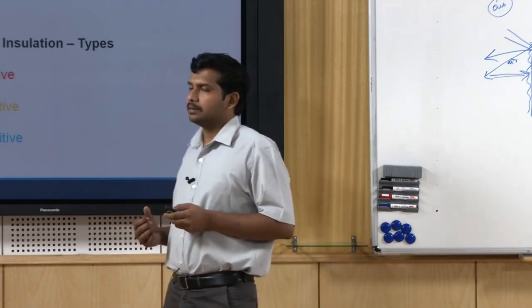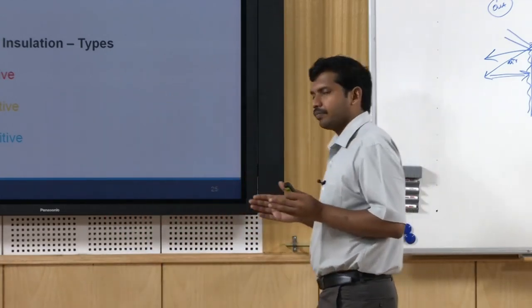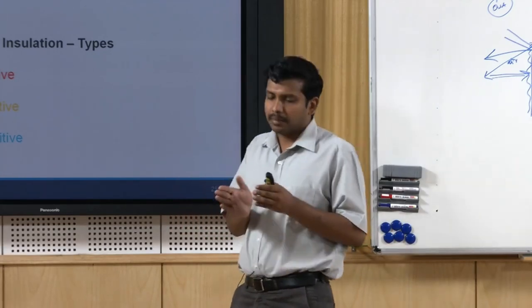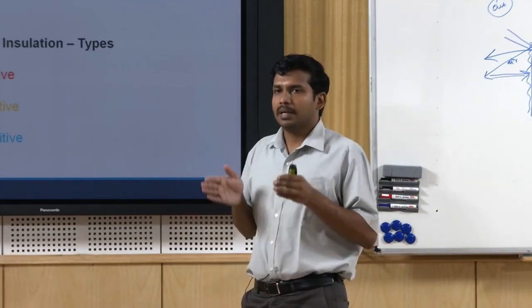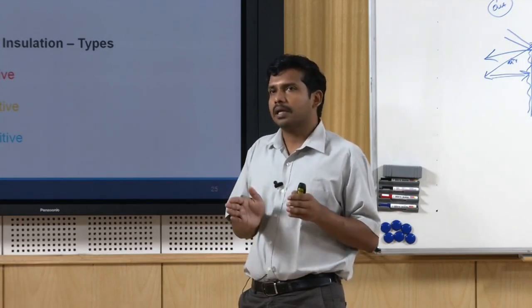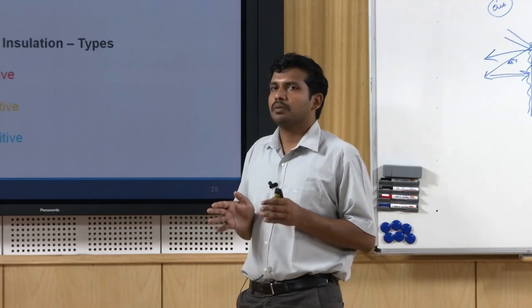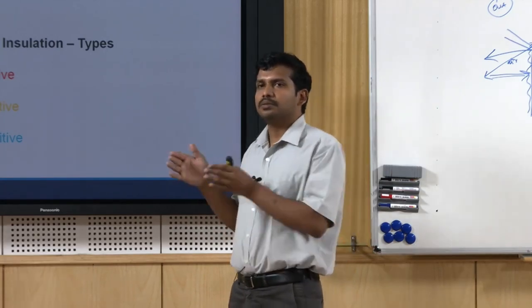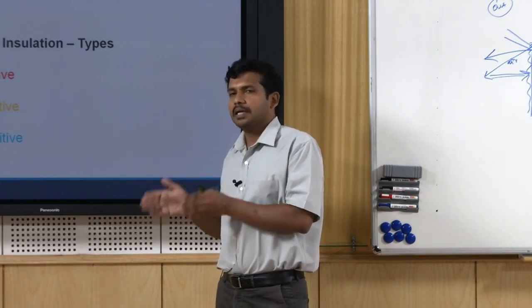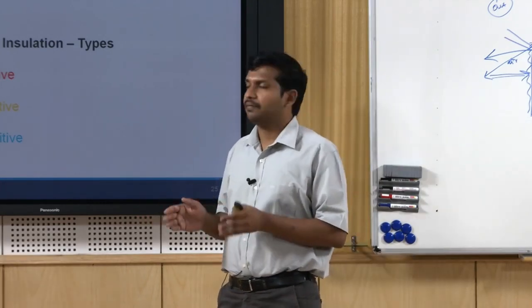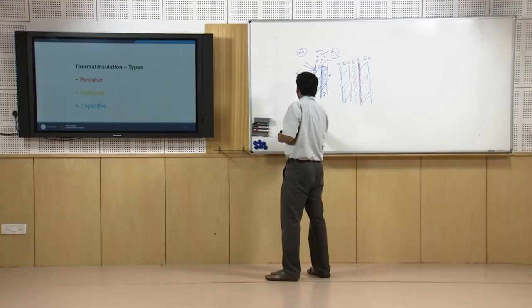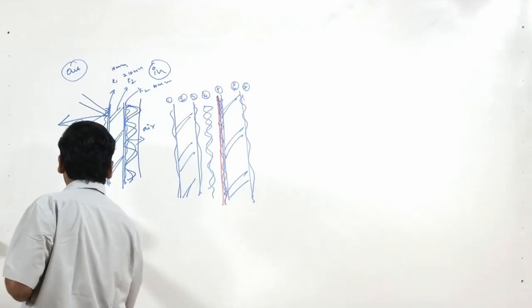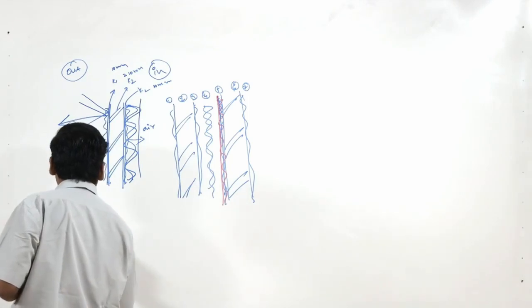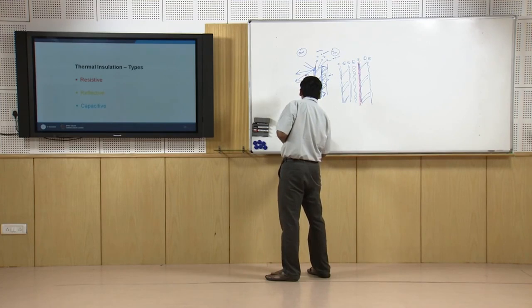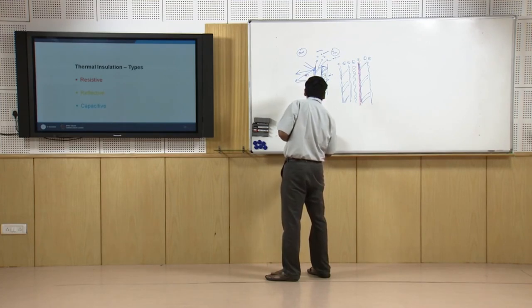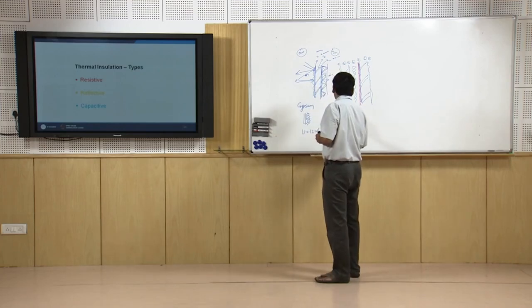But what one needs to realize is there is a lot of difference between an insulated wall. Say, imagine you have a gypsum wall, which is a thin sheet, plus 50 mm glass wool insulation. You can manage a U value of something close to 1 or 1.2 watts per meter square Kelvin. Compare this with the 230 mm concrete wall, which has a U value of 3.5. Now, I am talking about two different things. First is a gypsum panel, and then you have insulation. Imagine the U value is 1.2 watts per meter square Kelvin. Then I have a concrete wall.